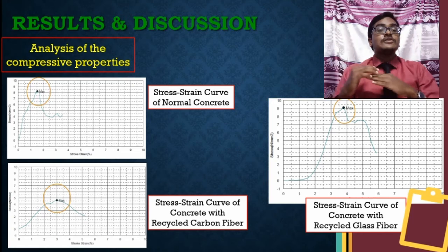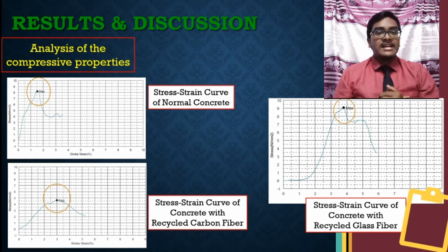Okay, from the graph we can also calculate Young's modulus. The Young's modulus for normal concrete is about 4.50 megapascal. The addition of recycled glass fiber to concrete results in an increase in the Young's modulus, before it decreases with the addition of recycled carbon fiber. The trend was similar to the ultimate tensile strength. The highest Young's modulus was found at about 6.92 megapascal, which belongs to the concrete with glass fiber.